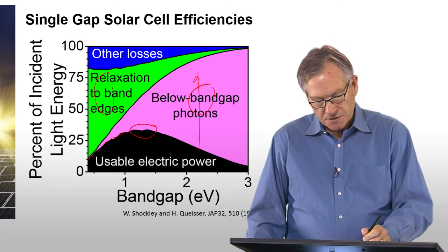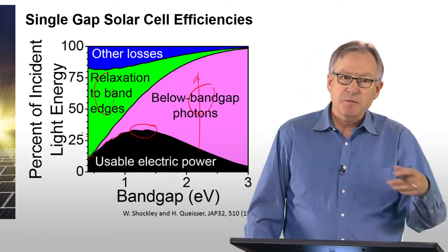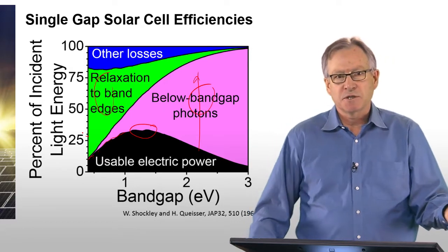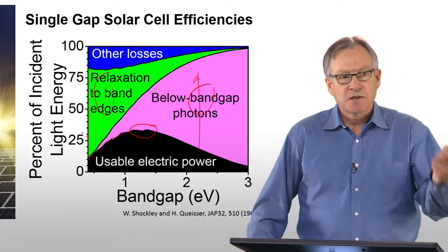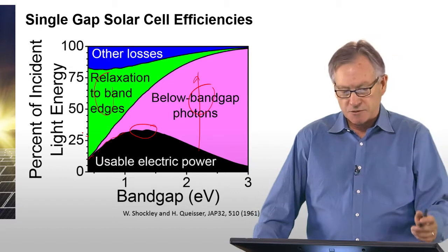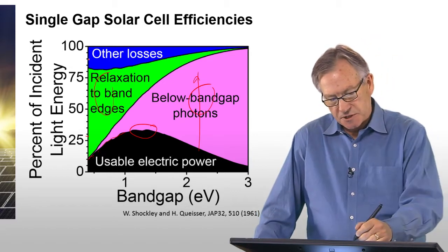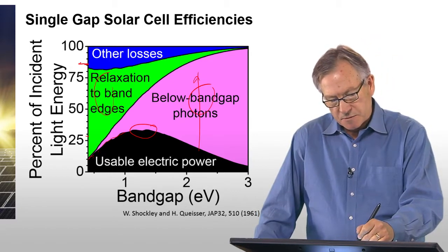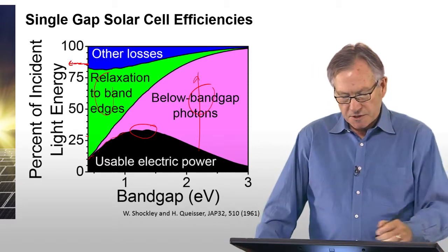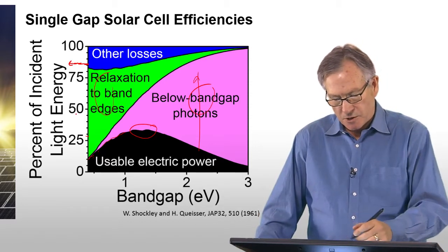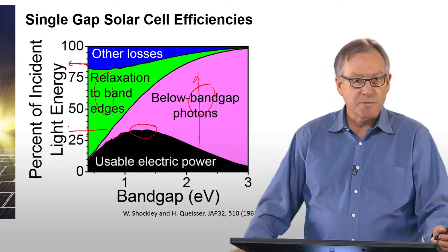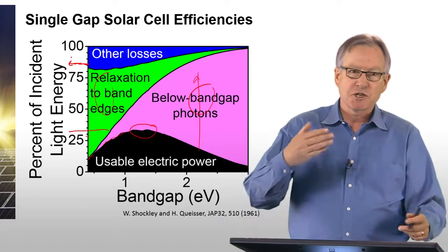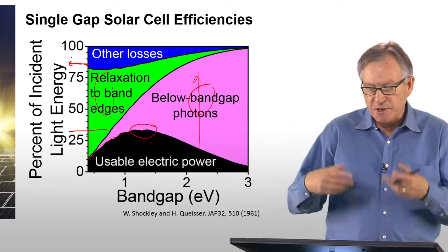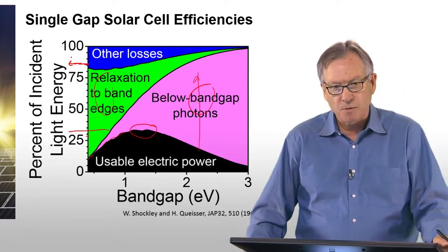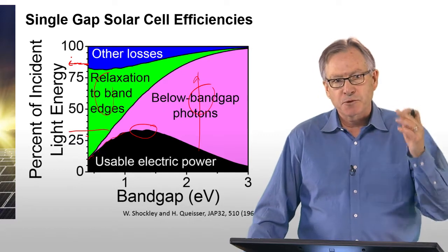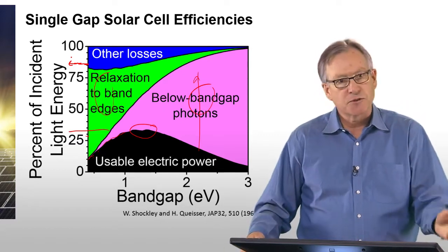However, this efficiency, this 33%, is much less than the maximum thermodynamic conversion efficiency, based on pure thermodynamics, of sunlight to usable energy, in particular electricity. That energy is closer to 86%, which is up here. And you can see that there's a large difference between where solar cells are, at 33% maximum efficiency, and where they could potentially be in terms of thermodynamic efficiency of 86%. And that's part of what these advanced concept or third generation types of cells are trying to address.